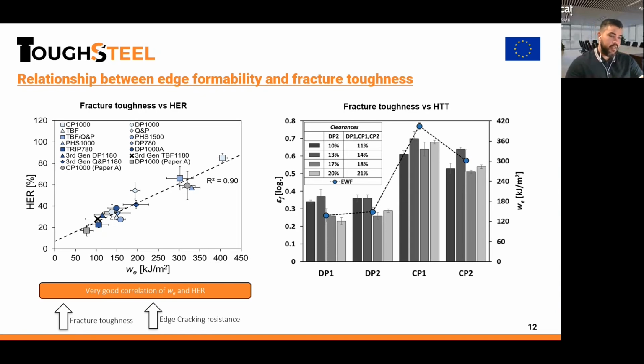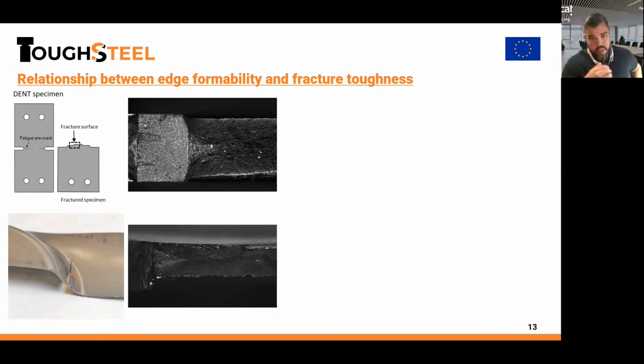Now, what is the physical relationship that explains the similar trend between fracture toughness and edge fracture? It is reported in the literature that the fracture mechanisms occurring during both fracture mechanics tests and edge fracture are pretty similar. Also, we have seen in the previous slide, from the scanning electron microscope images, that cracking in the end is a nucleation and propagation of cracks.